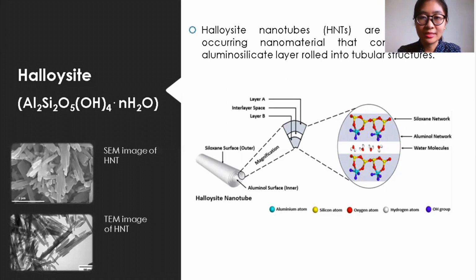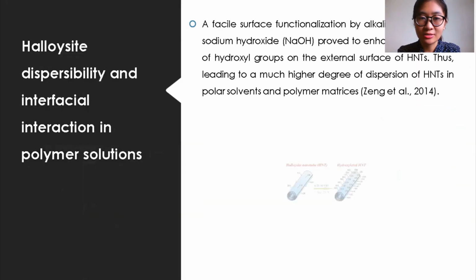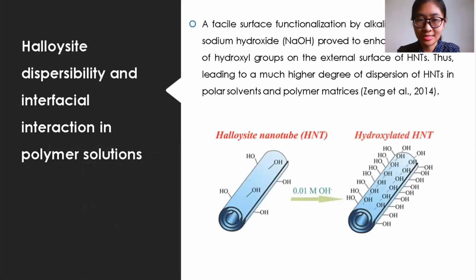However, it will be treated with mild alkaline solution, which is the novelty of the study, in order to enhance the density of hydroxyl groups on the external surface of HNTs, thus leading to a much higher degree of dispersion and interfacial interaction of HNTs in polar solvents and polymer matrices.